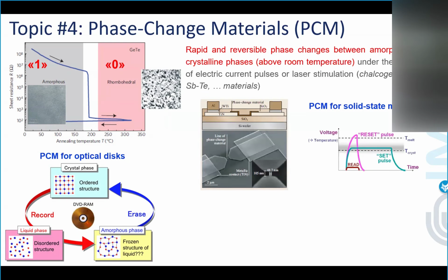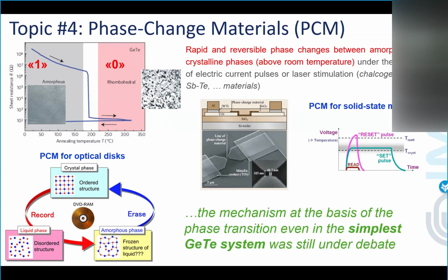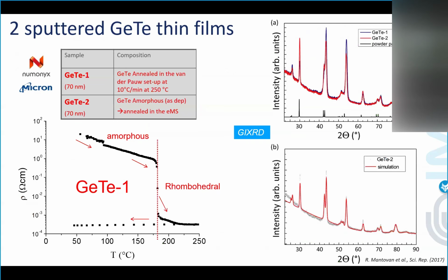They are sold already in several devices, but the mechanisms at the basis of this phase transition at the atomic level are still under debate today, and at that time they were for sure. So what we did, we fortunately had access to a state-of-the-art sample, germanium telluride from what was at that time Numonyx, then changing to Micron, big companies. And in our laboratory, we tracked the phase transition by doing resistivity versus temperature, and it showed what was expected, and we identified 180 Celsius as the transition temperature.